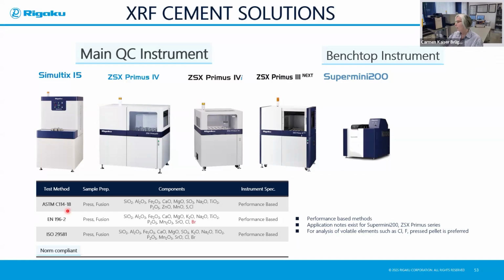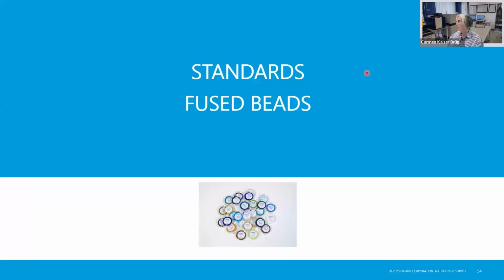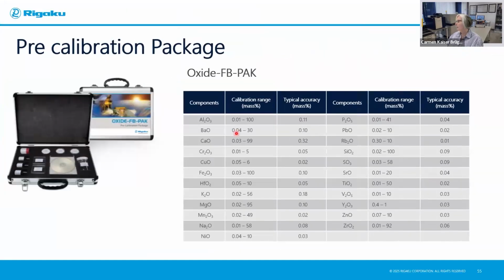Okay, so let's talk about some of these international norms. So if we look at the ISO 29581 for fusion, we have many fused bead standards that are available to set up these calibration methods. So one of them is the pre-calibration package that we can offer. And at Rigaku, we call it an oxide fused bead pack. So it's a very wide calibration range that you can see here. But it's not good enough for the analysis of the cement. So therefore, we have other solutions that we can show you because, of course, the cement needs to have a narrower range and not such a wide range.